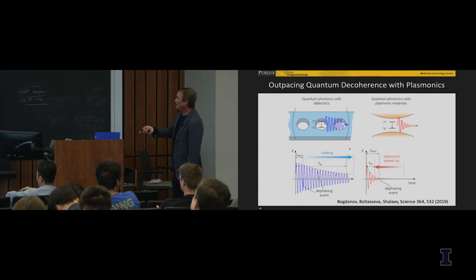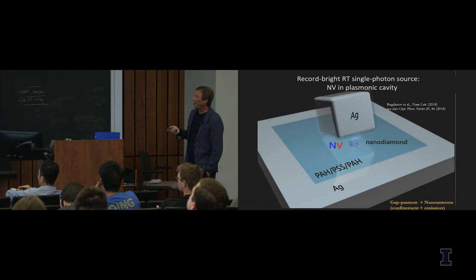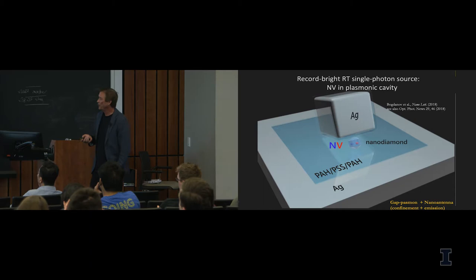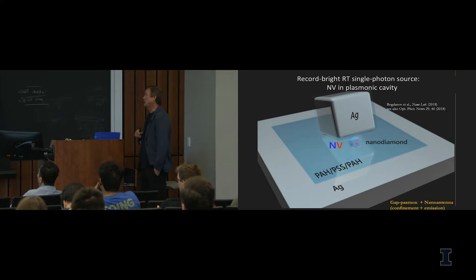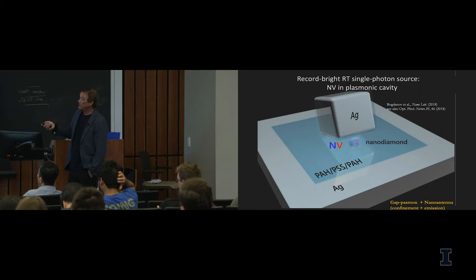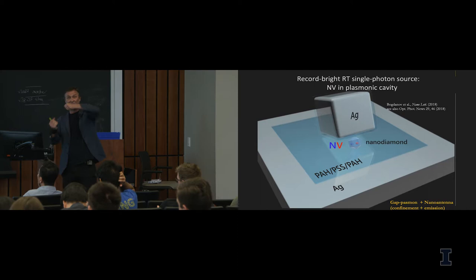So how to do it? The idea we have in mind is to use gap plasmons, which could be accomplished by placing a single crystal silver cube atop a single crystal silver film. And if I put inside some quantum emitter, in our case a nanodiamond with, for example, a nitrogen vacancy, although we are now working on other types of emitters, then the size of the gap would be basically dictated by the size of the nanodiamond, which could be very small. And that's where electromagnetic radiation would be confined. That's where you get this Purcell enhancement.